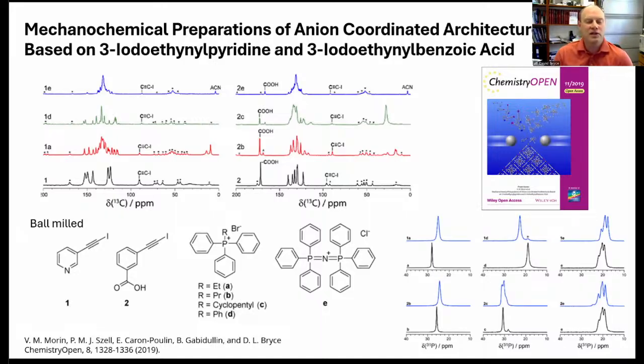And we prepared these cocrystals using ball milling, so pretty standard conditions. I don't have the conditions up on the slide here, but the point here is to show you what kind of monitoring capabilities we can get with solid state NMR. So again, with no workup, no purification, no growth of single crystals. The top left here, I've got carbon-13 cross-polarization, magic angle spinning NMR spectra. So these are spectra of the powders that come out, acquired with fast magic angle spinning on the order of 10 kilohertz to give us high-resolution carbon NMR spectra analogous to what we would see in solution. But of course, we're looking at our intact solid products from the ball mill.